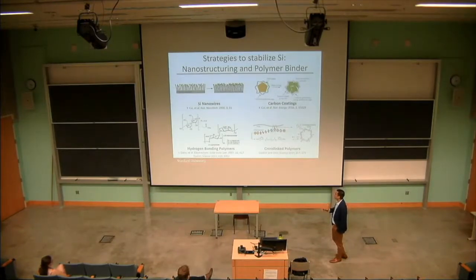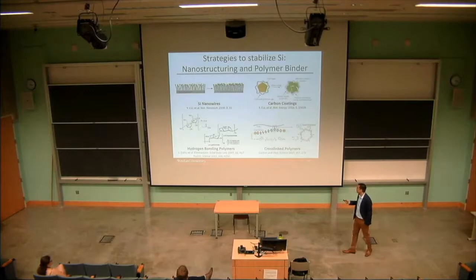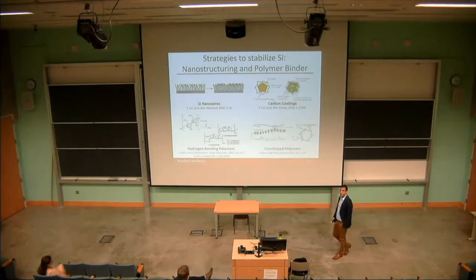And so hydrogen bonding polymers have been an extremely successful and popular approach to this. Carbohydrates specifically, and then acid polymers have been very, very successful. And the reason these work so well is because the hydrogen bonding groups of these polymers associate with the silicon surface, and so they maintain strong connectivity of the particles with the carbon and the current collector. And then finally, so that's more of a secondary cross-linking effect or a physical cross-linking. You can also covalently cross-link these polymers, and then you have an elastic binder material that leads to very high mechanical stability of your electrode, and these have also been shown to have quite good cycling performance.